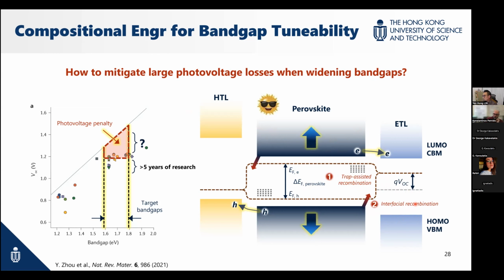This is even more severe when we increase the bandgap, because when we mix different materials, basically they don't like each other. We know about halide segregation. We talked about that just in the previous work, and certainly we introduce more defects into the perovskite material. So this is why it reaches a certain level and becomes a plateau. What we actually want is for perovskite to be just as good as the best semiconductor material, which is gallium arsenide. Gallium arsenide is so close to the theoretical limit that the photovoltage penalty is only 50 millivolts.